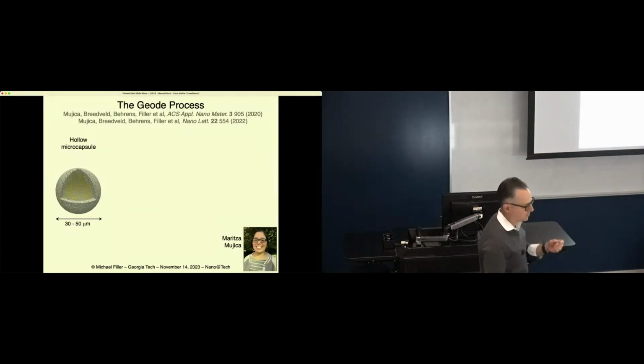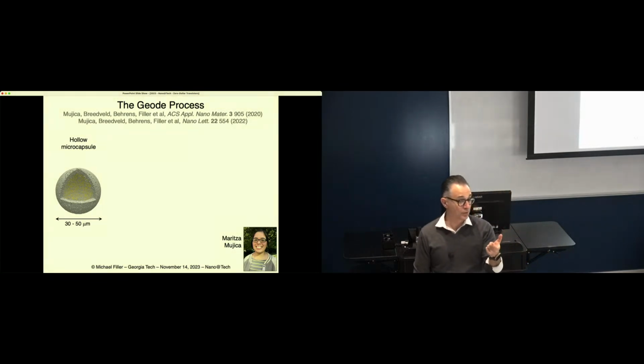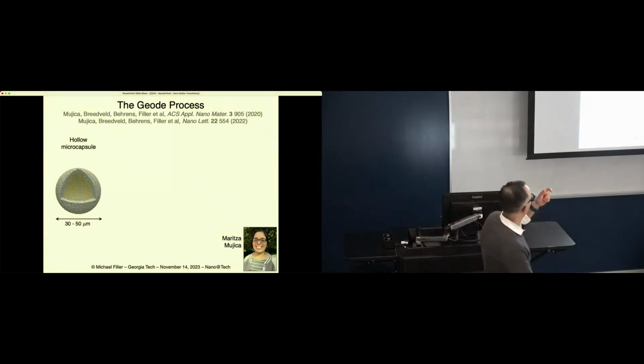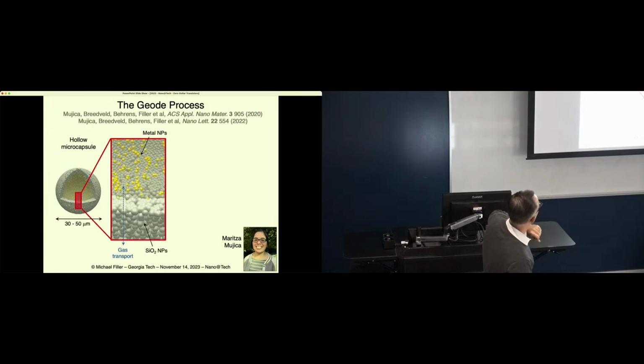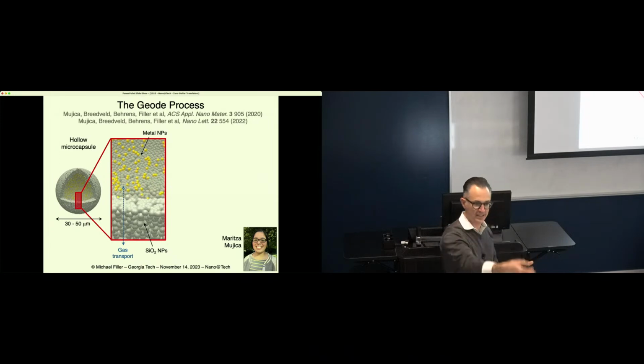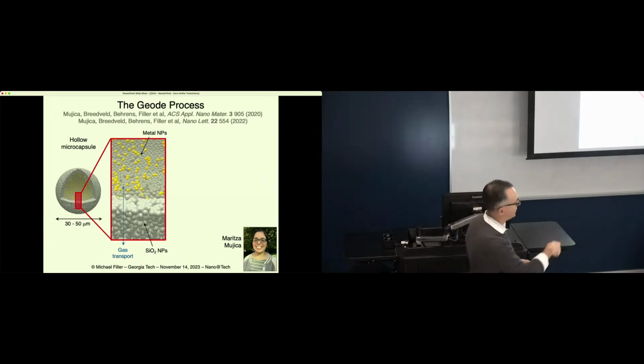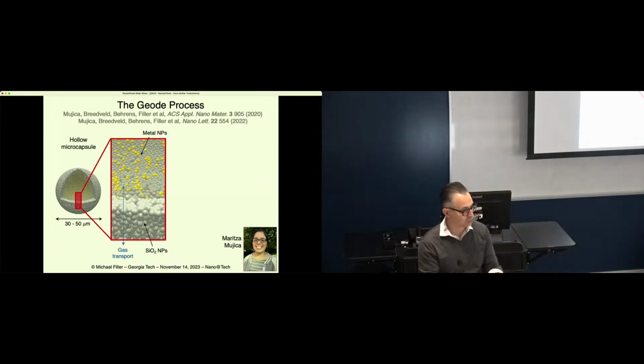And so we've been trying to do the same thing, but more on the micro scale. Okay? So on the left is a picture of what one of these microcapsules might look like, and I'll show you some real images in a second. They're about 30 to 50 microns in diameter. They have a porous shell that allows gas to transport efficiently from outside to inside. And we line the interior with the metal nanoparticles that drive and catalyze nanowire growth.